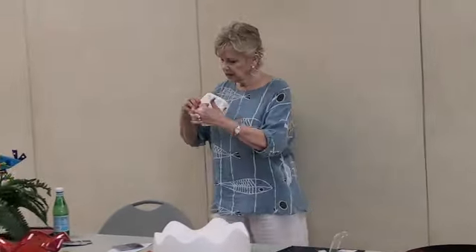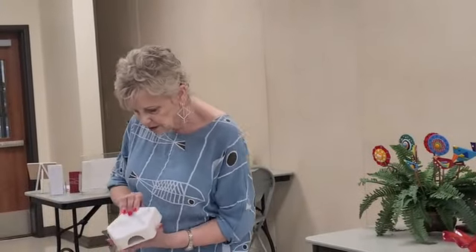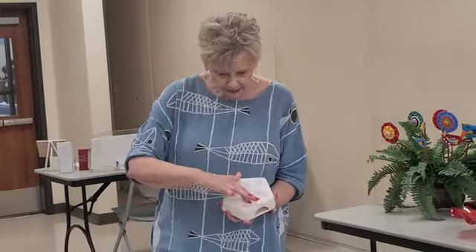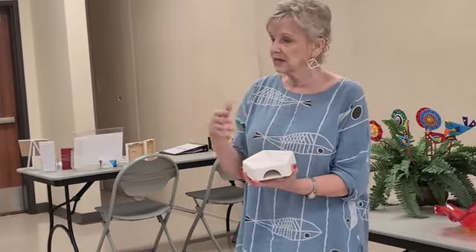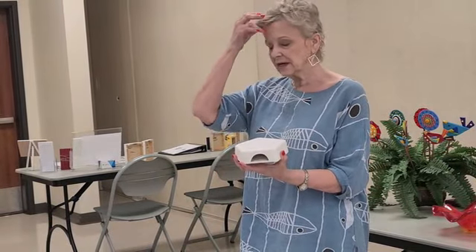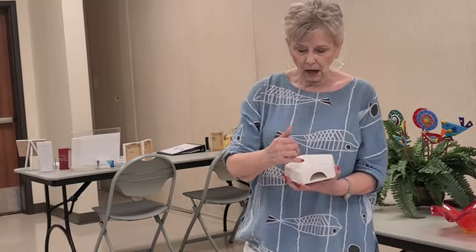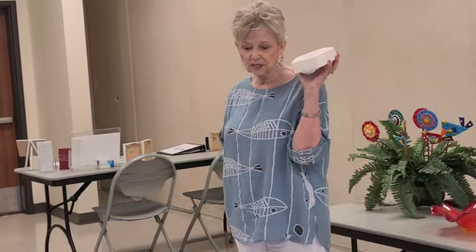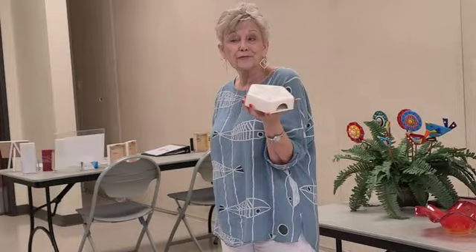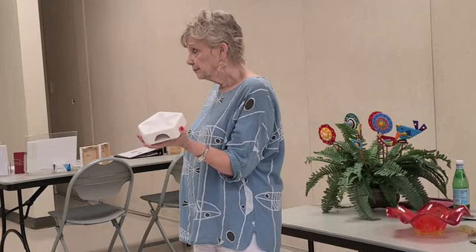this has all the detail in it. It has all the bumps on the starfish. So I put the colored frit down in here, and then I started piling big pieces of clear glass in there, because I keep jars and jars of it from things that I cut. Pile it on top so it doesn't come over the top, but fills in pretty well. Then you put this in the kiln and fuse it to probably about 1500 for, I would say, 30 or 40 minutes, which is a long time.